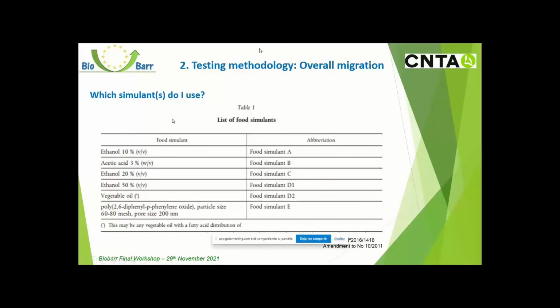Yes. Regarding the food simulants, it's often impractical to perform migration tests on actual food under real conditions. Therefore, the tests are performed on food contact simulants under simulated test conditions. So, determining which simulants apply will vary based on the intended food contact use. In our case, we use simulant A, which is assigned for non-acidic foods. Also, food simulant B, assigned for acidic food, and food simulant D2, assigned for fatty foods.